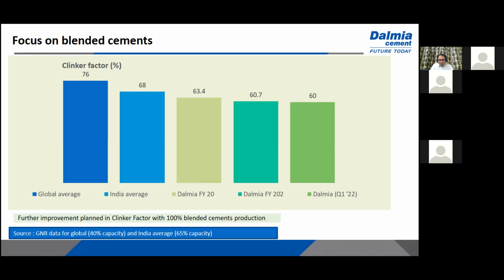So if we do that, at the same time, we are also helping thermal power plants to operate properly. We are also helping the steel industry to dispose their waste. Nearly all the blast furnace slag, which is a waste of the steel industry, is consumed by the cement industry, and nearly 50 to 60% of the fly ash of the thermal power plants is consumed by the cement industry, which allows them to function seamlessly.